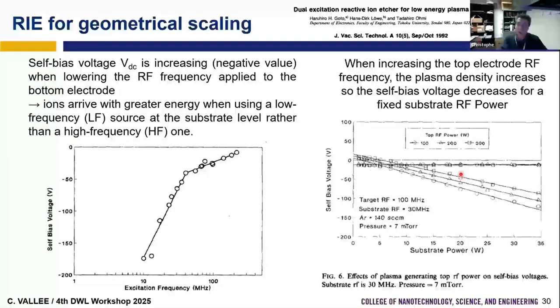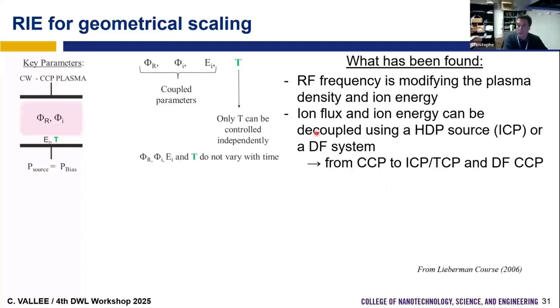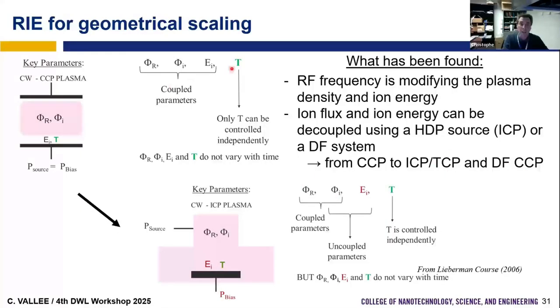So they have all the results that we had in HDP source, where we have an independent control of the plasma density and the ion flux, and the denser the plasma, the lower the ion energy. So this is what has been found. So we found that radio frequency can modify the plasma density and ion energy, and the ion flux and ion energy can be decoupled using either a HDP source, for example, an inductive system, or a dual frequency system. And so this is why we shifted from CCP plasma reactor to ICP or TCP plasma reactor or dual frequency CCP reactor. Now, instead of having all parameters coupled, we can decouple the plasma parameter, like the flux, from the substrate surface parameter, like the energy. So ion flux and ion energy now are decoupled. But we can see that with this design, we still have all parameters that do not vary with time.